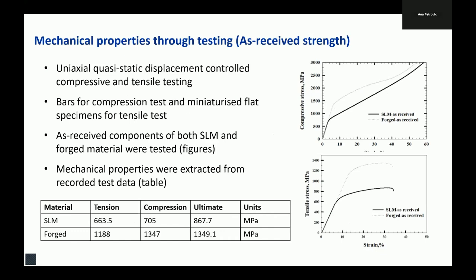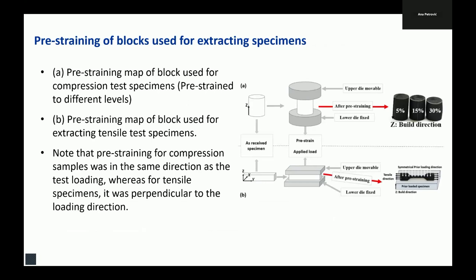If we start with the mechanical properties in the as received condition, you can see the SLM in compression and in tension, and also the forged in tension and compression, both in the as received condition. And this table summarizes the values that we have. You can see that the forged material, as we expect, has significantly higher strength compared to that. But we know the obvious advantages of the selective laser melted technique, including the accuracy that we can get in the dimensioning, etc. And also the costs of the forging could be another contributing factor to going for this sort of technique for fabricating components of Inconel.